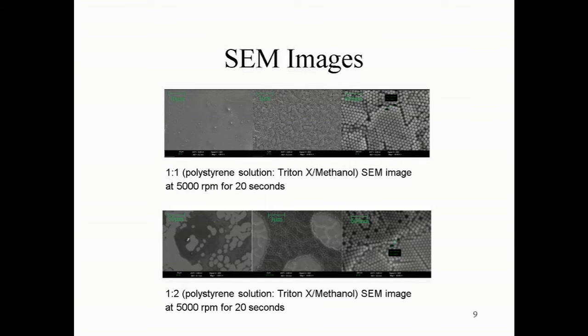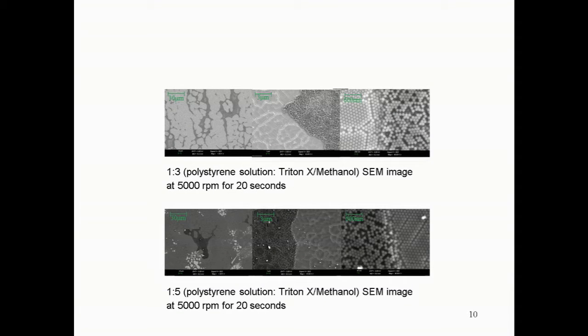We can see there were monolayers in both coatings but in a tangled structure, and the 1/2 proportion had heavily uncoated areas that we did not want. With the solution of 1/3 proportion, there were again uncoated areas with monolayers on the surface of the wafer. When we look at both proportions, we can see that 5000 rpm was not enough for polystyrene nanospheres to spread on the surface of the wafer. Therefore, we decided to increase the speed and time of the coating.